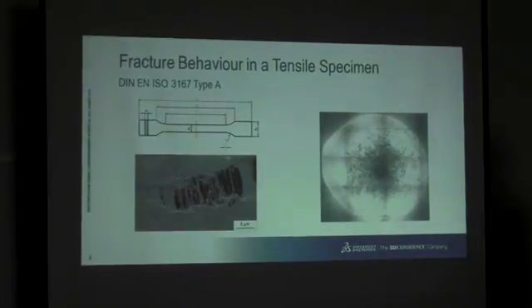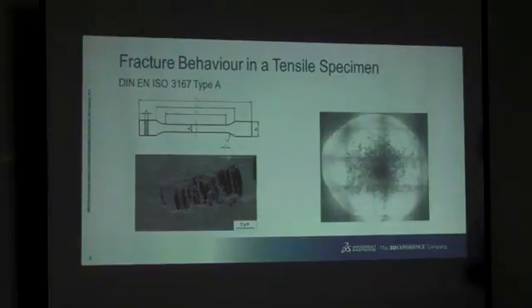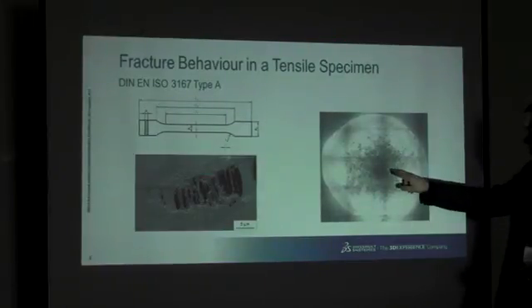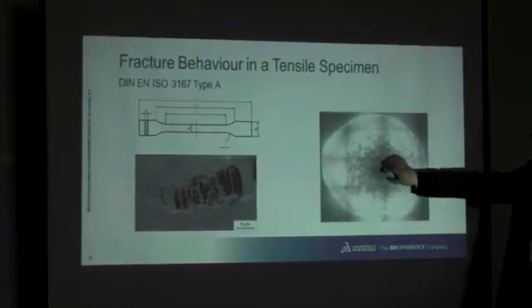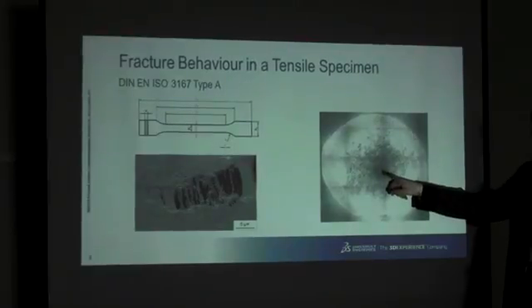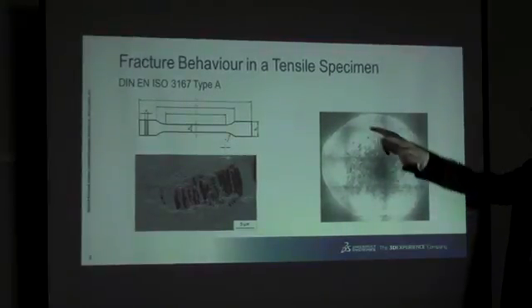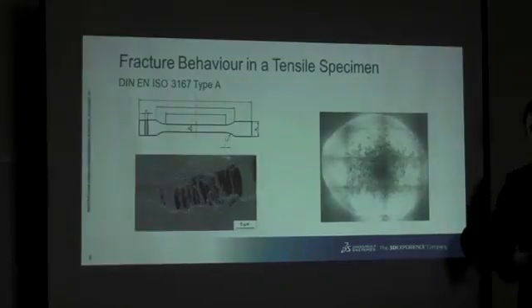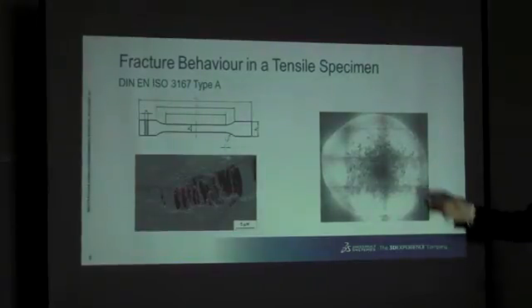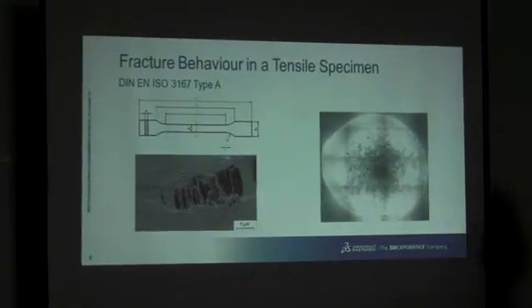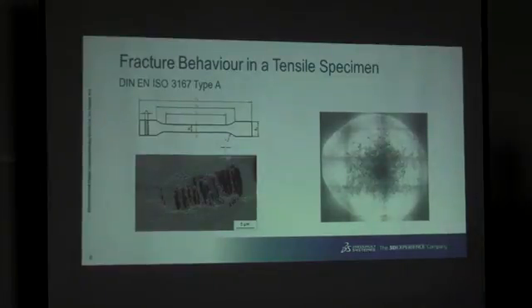Here is probably the more interesting one. This is a fracture surface of this very specimen. And what's happened is that a lot of voids have coalesced over time to form a lot larger voids. So you're looking at the cross-section of that specimen. And they've started to grow radially outwards until they came in contact with the skin. The lobe was too large, bam, ripped it apart. We'll look at the fracture surfaces in a second.